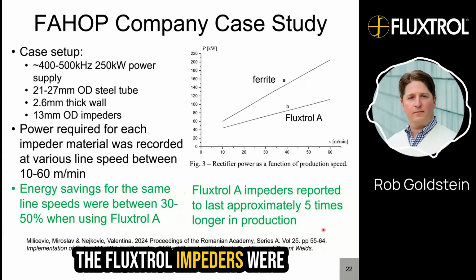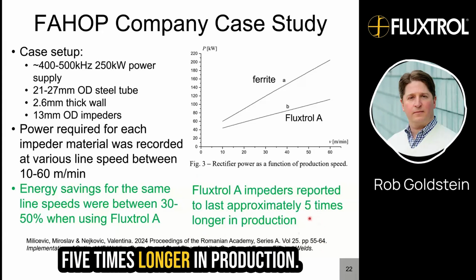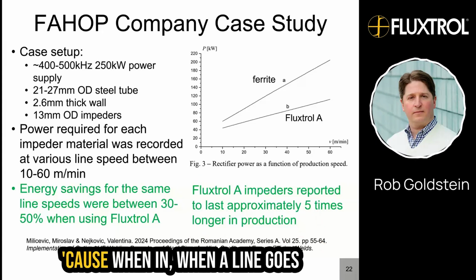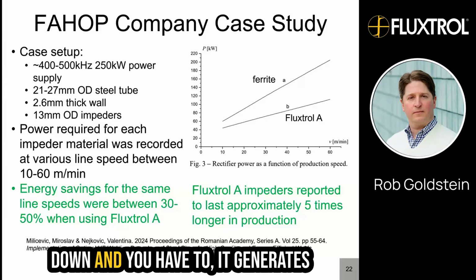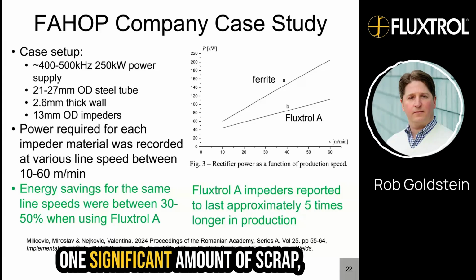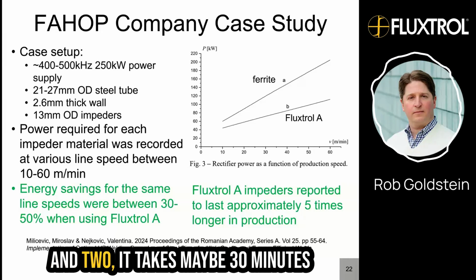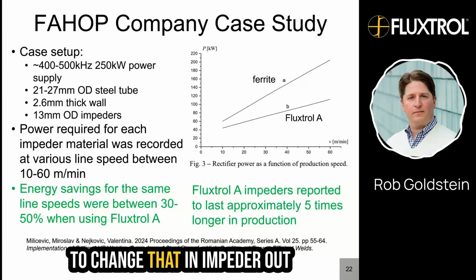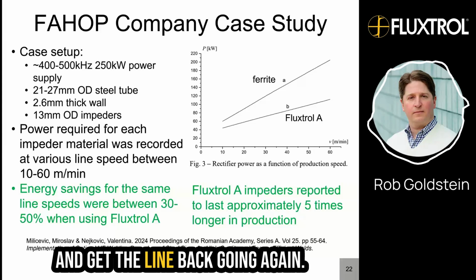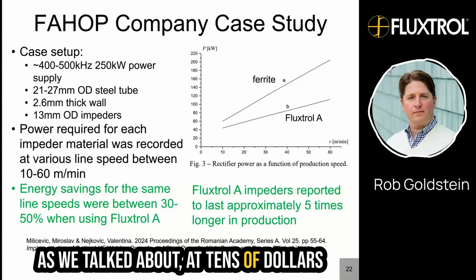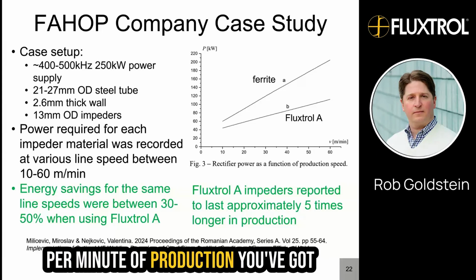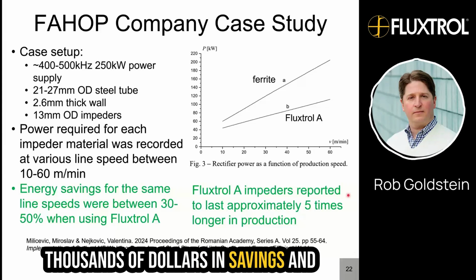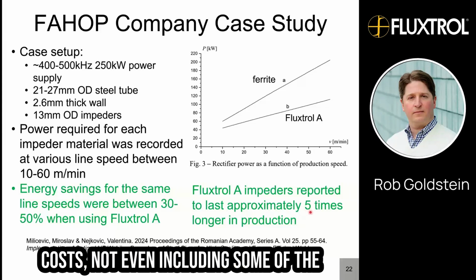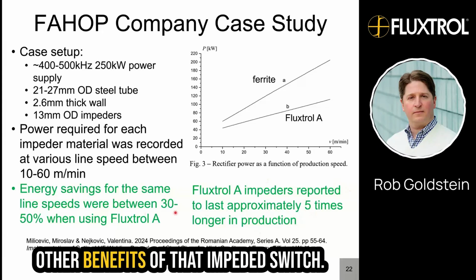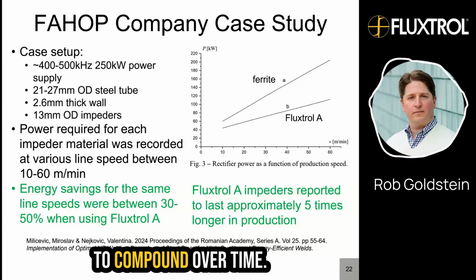The Fluxtrol impeders were reported to last approximately 5 times longer in production, which is huge because when a line goes down, it generates, one, a significant amount of scrap, and two, it takes maybe 30 minutes to change that impeder out and get the line back going again. As we talked about, at tens of dollars per minute of production, you've got thousands of dollars in savings and costs, not even including some of the other benefits of that impeder switch, and those really start to compound over time.